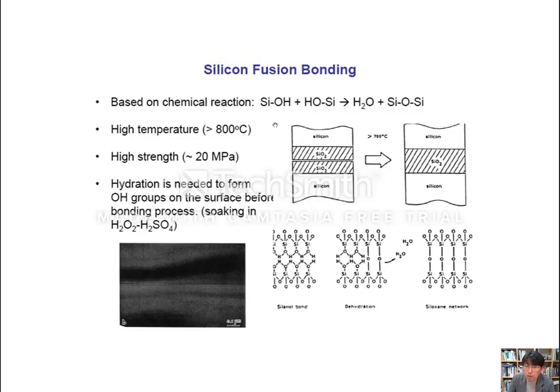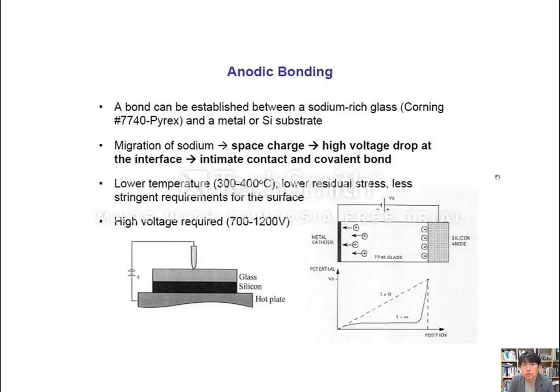Then after you put them together, you apply a high temperature of more than 700 or 800 degrees C, and you apply a certain pressure between the two. Then the separated silicon dioxide becomes one layer. Eventually these two substrates are bonded, like a bonded chip, right? So that's what happens here. This is called silicon fusion bonding between two silicon substrates by using the silicon dioxide on top of each substrate. The other bonding method is called anodic bonding.